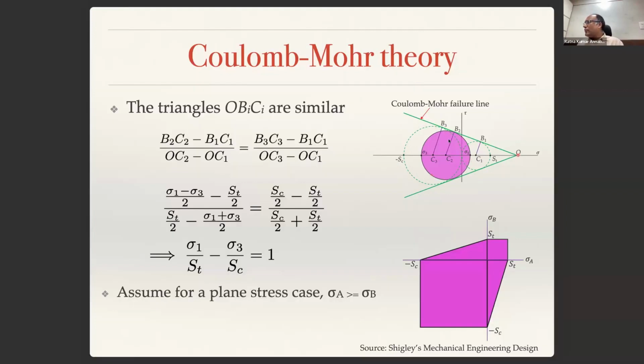And now, once you have the uniaxial tension circle and the uniaxial compression circle, you can draw a Mohr-Coulomb line, or the failure line, and that decides what my tau is and so on. Now, if you draw a stress state corresponding to sigma 1 and sigma 3, and this circle becomes tangent to this line, that means it is failing, right?